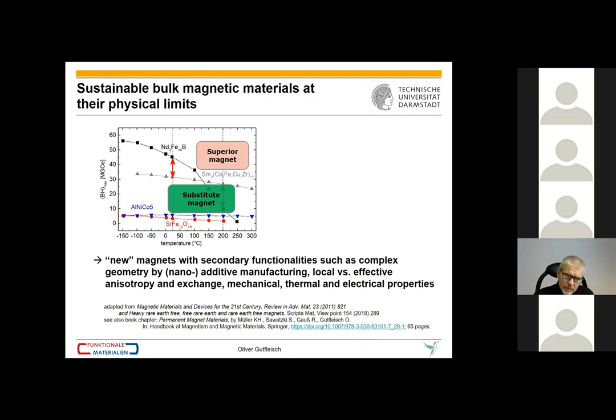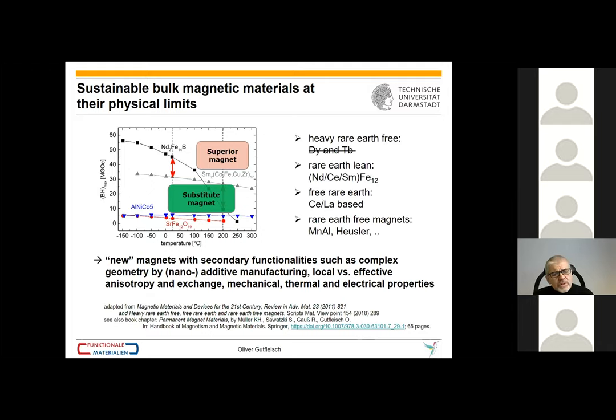So this is then our playground, where we also give more emphasis to secondary functionalities in addition to these prime figures of merit in terms of magnetic performance: additive manufacturing, which Dieter Suess, as a follow-up speaker, will explore more, and then the localized material states, but also directional properties, for example, in terms of thermal and electric conductivity. So our playground is that we want to make heavy rare earth free magnets, first of all, that we look into rare earth lean systems, like a 1-12 type compound, that we want to utilize what we call the free rare earths. For example, cerium and lanthanum are cheap and abundant rare earths, so there's nothing rare about them. And then ultimately also moving to rare earth free magnets like manganese aluminium, or Heusler type materials.